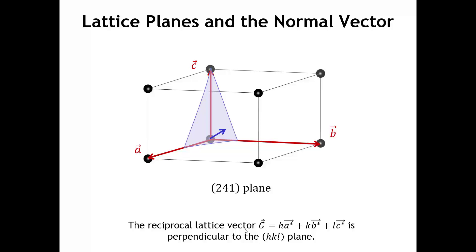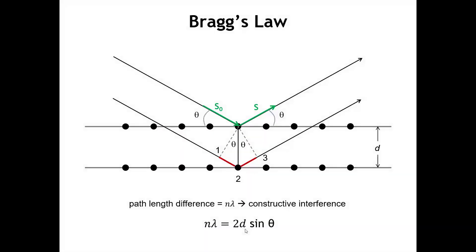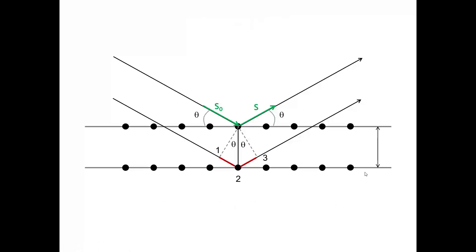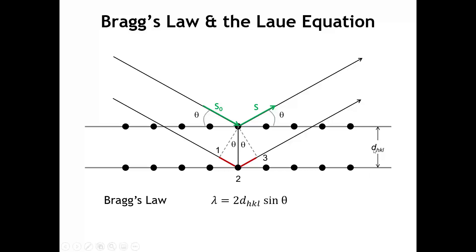What does this have to do with diffraction and Bragg's law? The planes of atoms that are scattering the incoming x-rays are the lattice planes HKL. So if we rewrite Bragg's law with D_HKL — the distance between two specific planes in a crystal lattice — and we drop the N in front of lambda, saying the path length difference is just one lambda, this is the picture that describes the conditions giving rise to constructive interference when reflecting x-rays off a series of lattice planes.